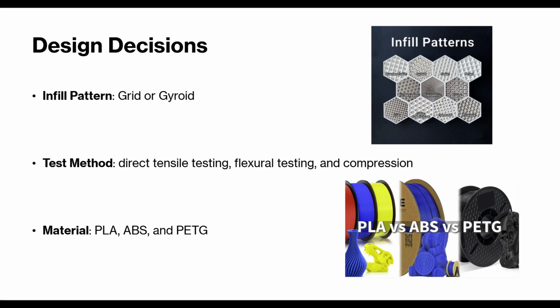To ensure accurate determination of Young's modulus, we evaluated multiple design alternatives for specimen preparation and testing. For infill pattern, we tested grid and gyroid structures. The grid offered consistent force distribution. However, we chose gyroid because it showed better results for the tensile test. For test method, we compared direct tensile testing, flexure testing, and compression. Tensile testing was chosen because of its first-order response and direct modulus calculation. For material, we compared PLA, ABS, and PETG. PLA was selected because it is more cost-effective while still providing sufficient mechanical strength and stiffness to meet the project's performance requirement.